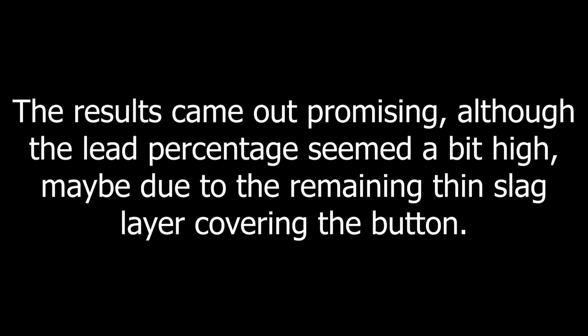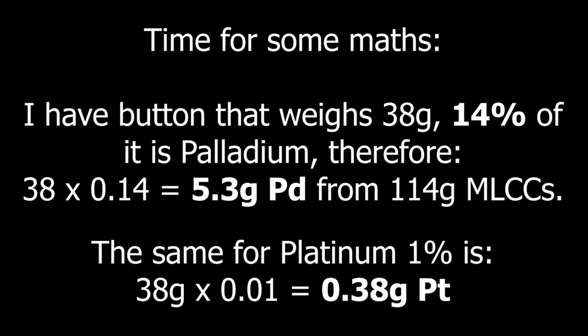The results came out promising, although the lead percentage seemed a bit high, maybe due to the remaining thin slag layer covering the button. Time for math. I have a button that weighs 38 grams, 14% of it is palladium, therefore 38 by 0.14 equals 5.3 grams palladium from 114 grams MLCCs. The same for platinum. 1% is 38 grams by 0.01 equals 0.38 grams platinum.